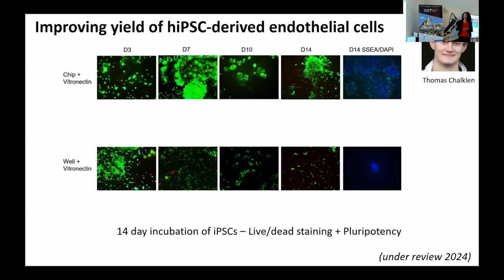My student Thomas Chalklen did this using iPSC-derived endothelial cells. We did this work with the Cambridge Blood Center, where they were trying to improve the amount of endothelial cells they were producing from their normal chemical concoction. This is an example of what they have, looking over a 14-day incubation period of iPSCs. This is the standard well plus vitronectin. You put down your cells, you start the differentiation process, and this is what they end up with. Whereas the same experiment, when we do it on our chips, you can see this is about a 67% improvement in the yield. So there is something about being able to control that mechanical environment, and possibly because these are piezoelectric polymers, the electrical environment, that is giving rise to this effect.